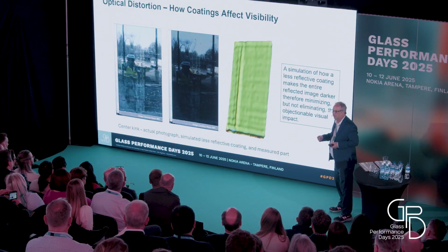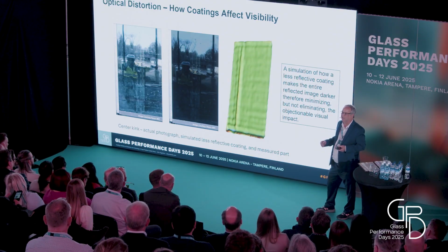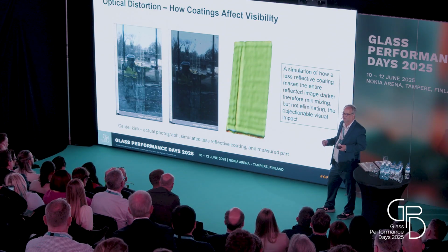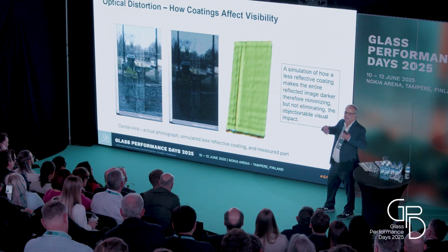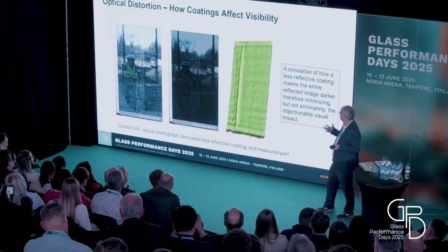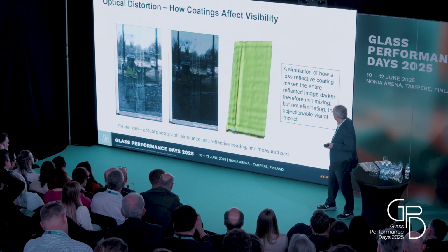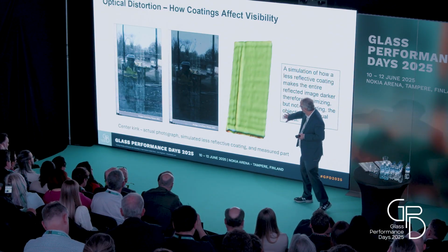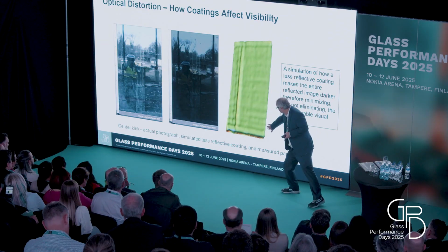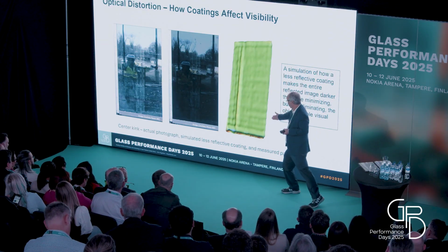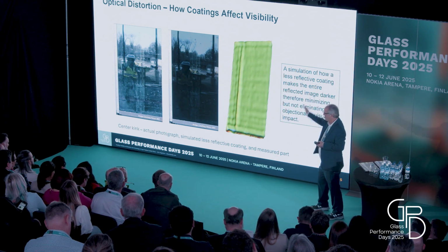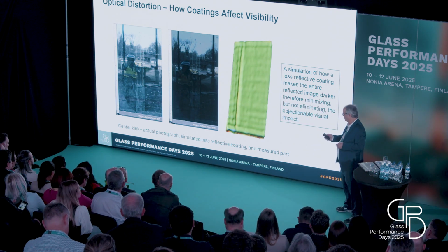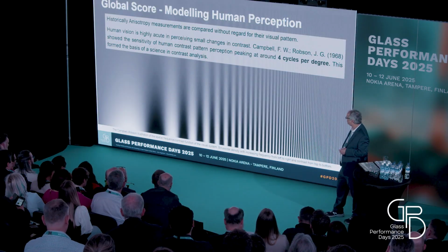The visibility distortion is directly related to the reflectivity of the coating. It really doesn't involve a lot of colors and a lot of internal reflections. It's just the reflectivity of the coating. And this is an actual measurement out of a machine. So you can see clearly that there's a very light, what I would call grey, very low level roll wave going that way, but this very obvious level of center kink distortion.